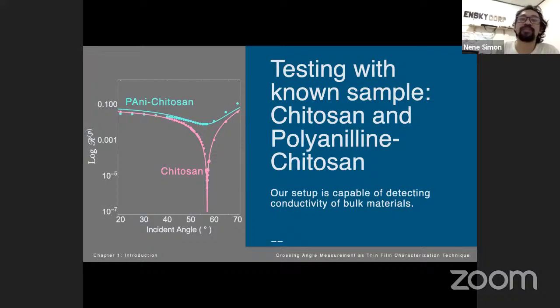So we test run our setup with various samples, one of which are the polymer samples. Here I'm showing you a reflectivity plot of a chitosan sample. This is the P reflectivity plot in logarithmic scale. And notice that the chitosan is displaying a Brewster angle. So this dip here, this nice dip here, is the location of the Brewster angle. The other curve is the polyaniline chitosan sample, the reflectivity of the PANI chitosan.